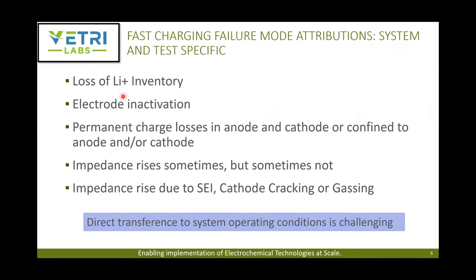The loss of the lithium ion inventory for charging and discharging, the electrode inactivation, which we touched on, permanent charge losses in the anode and cathode. Essentially, the cathode and anode don't have the capacity to accept or intercalate enough lithium into their material. The impedance rises in some cases. In some cases, they did not see that. And then the SEI, cathode cracking and gassing that we touched upon.